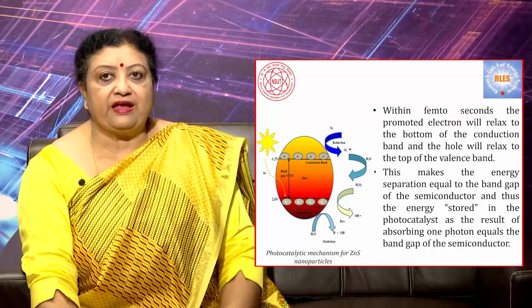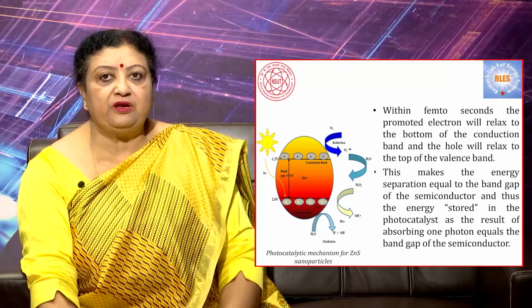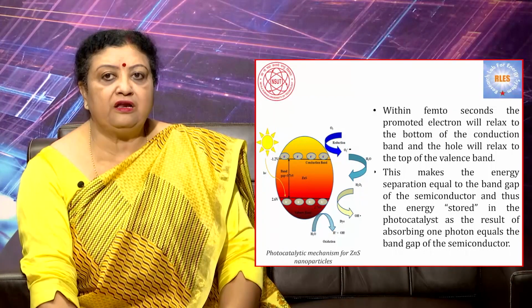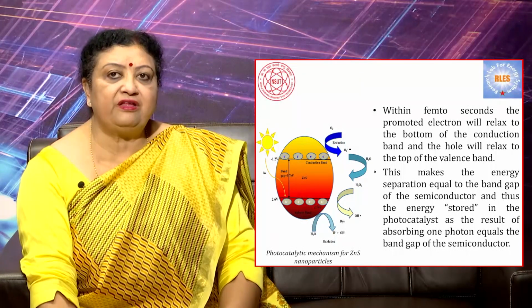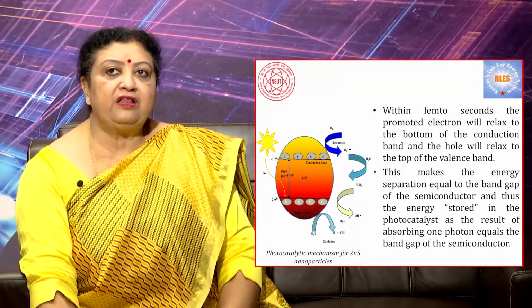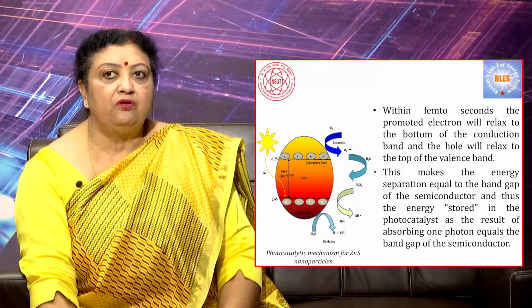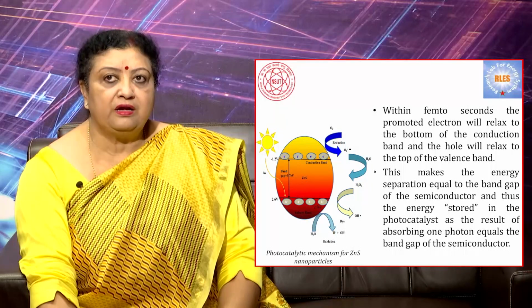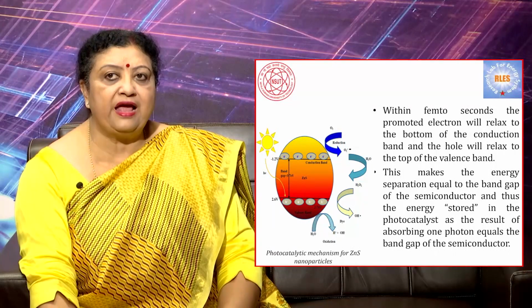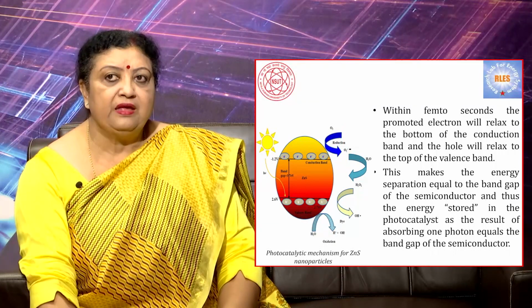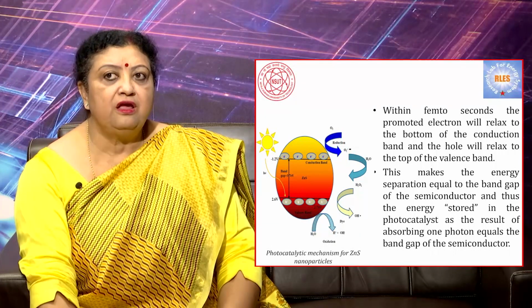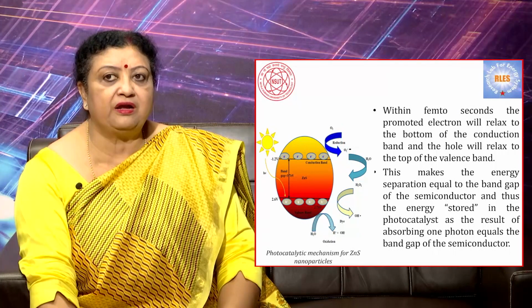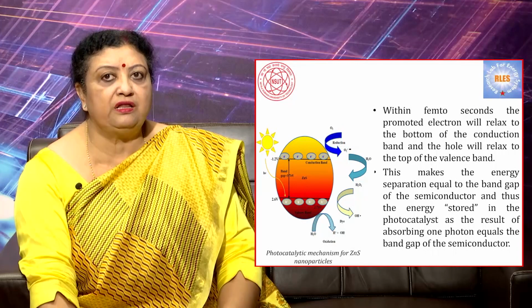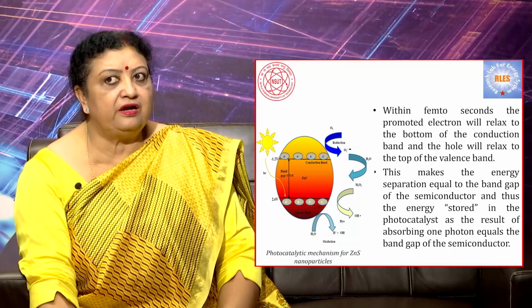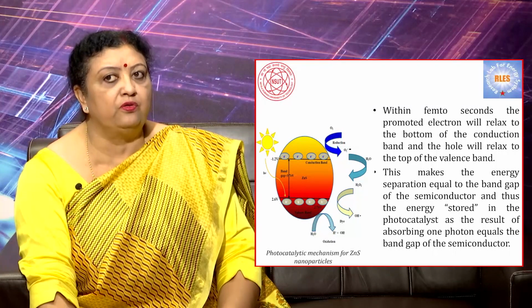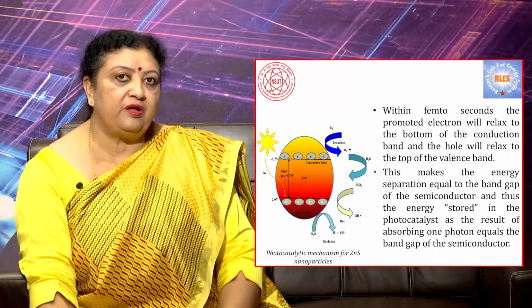So, within the femtosecond, which you are able to see from this particular picture here, that is the photocatalytic mechanism, how it is taking place in the ZnS nanoparticles. Within the femtosecond, the promoted electron will relax to the bottom of the conduction band and the hole will relax to the top of the valence band. This makes the energy separation equal to the band gap of the semiconductor, and thus the energy stored in the photocatalyst as the result of absorbing one photon equals the band gap of the semiconductor.